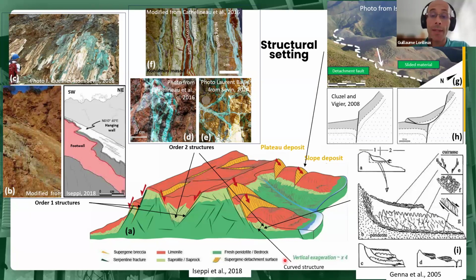The tectonic activity may be responsible for simultaneous formation of nickel-rich silicate veins, a rapid process related to hydraulic fracturing and crack-seal, and the redistribution of nickel downward by weathering, as alteration is enhanced and favored in fracture zones where permeability is higher. And this would explain the actual nickel enrichments described in one of the first slides, with this downward leaching of nickel.